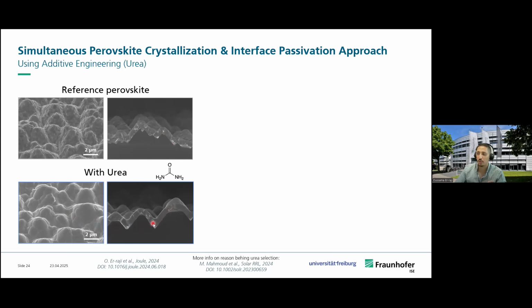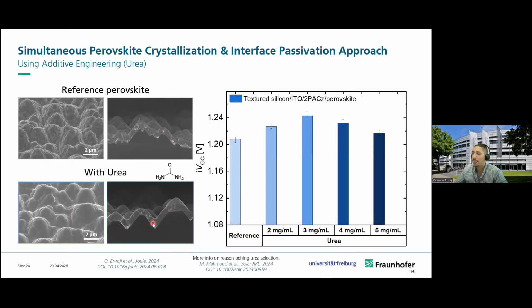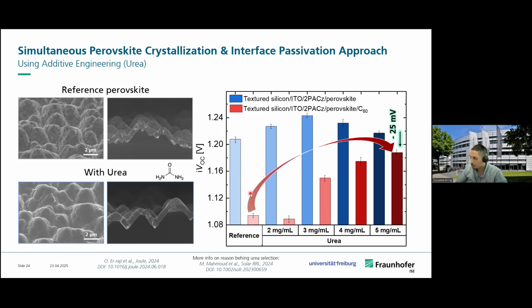These improvements in structure and morphology were directly reflected in the optoelectronic quality. Here you can see again quasi-Fermi level splitting or iVOC measurements of the stack until perovskite. We have the reference here, and then different films with different urea concentrations. With the optimum concentration, we can get up to a 30 millivolt improvement in iVOC. Now, to our surprise, we saw that the impact of urea goes beyond the absorber. When we measured iVOC for a stack until C60, as we have observed before, in the reference case we have a high non-radiative recombination, a 110 millivolt drop. But when we measured that for the urea case, there was a big change. It was reduced to only 25 millivolt.